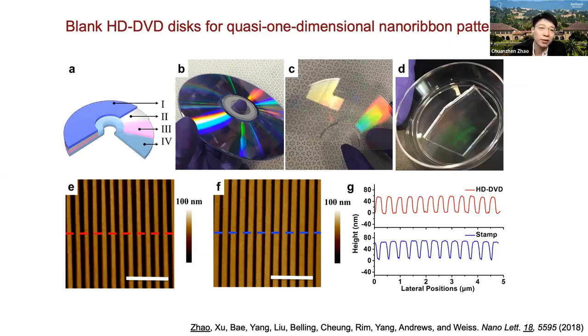If you take a look at the DVD, it has 4 layers, and you can separate them between layer 2 and 3 using just a razor blade. Layer 3 is just a dye layer, and you can rinse it off with ethanol, which gives you the substrate of the DVD that can be replicated easily using PDMS stamps. Those are some atomic force microscope images of the substrate of the DVD and also the patterned PDMS stamp once we replicate the feature from the DVD.